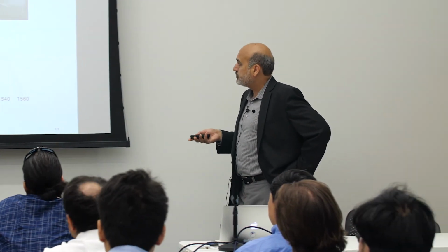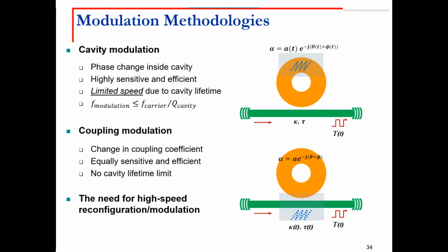Now, just to get into that modulation technology, I have a very simple cartoon that I like to show. So in conventional modulation, we typically change the refractive index of this material, and the resonance wavelength shifts, and as a result, signal goes from high to low, or vice versa, in the waveguide, which is bits 1 and 0. That's how modulation is done.